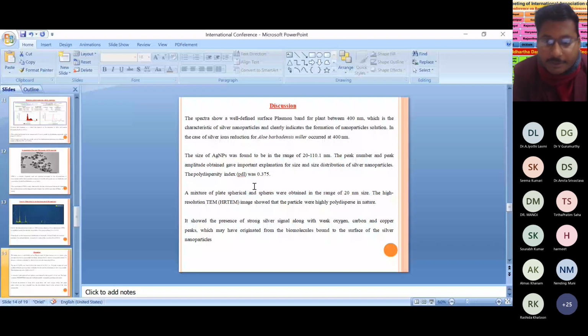The mixture of flat, spherical, and sphere-shaped particles was obtained by TEM, in the range of 20 to 50 nanometers in size. The high resolution TEM image shows the particles were highly polydispersed in nature. EDS shows the presence of a strong silver signal along with weak oxygen, carbon, and copper peaks, which may have originated from the biomolecules bound to the surface of the silver nanoparticles.